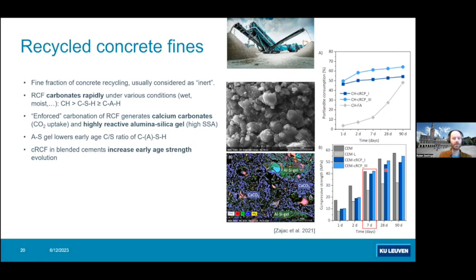And it's interesting to note that these materials are indeed inducing quite significant gain in strength. You can see, for instance, here in blue, the strength developments for the blended cements with carbonated recycled concrete fines. You can see a major increase by 7 days of the strength, up to the level of the reference Portland cement. So it's an interesting material to work with if you can get it really carbonated.